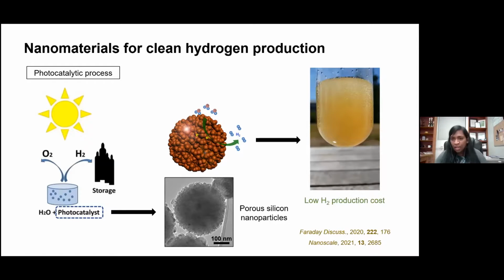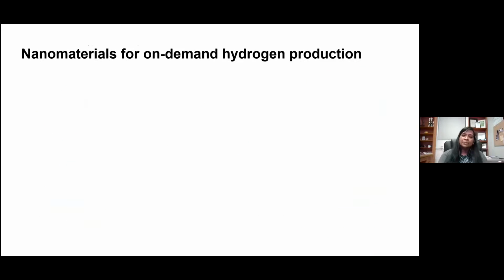So here is just the silicon photocatalyst suspended in water, and we have it out in the sunlight, and you can see that it's actually just splitting water and making hydrogen bubbles that you see evolving here. So you can see the system is much more simple, and because it's simple compared to the PV electrolyzer, this allows us to make hydrogen at a much lower cost than the PV electrolyzer system does. So we can now make hydrogen at least 1/4 the cost that PV electrolyzer systems do. So this is all great. So we have the electrochemical process, we have the photocatalytic process.